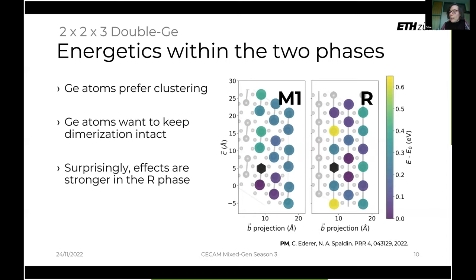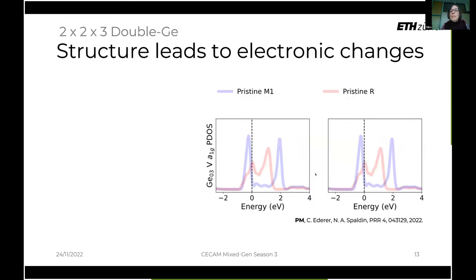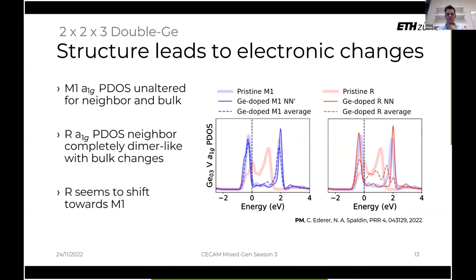And so you seem to be arguing that the germanium doping perturbs the rutile phase in the direction of the M1. So this is the part that I did not completely follow, because from your plot, I was rather getting the impression, and you said it, that the rutile phase gets more disordered. So I'm wondering why you actually interpret this as being closer to M1, rather than saying maybe it's so much disorder disturbed rutile phase that it is also insulating, but not because of the typical mechanism of the M1. That's of course a very good point.